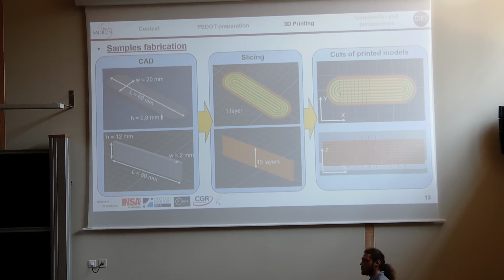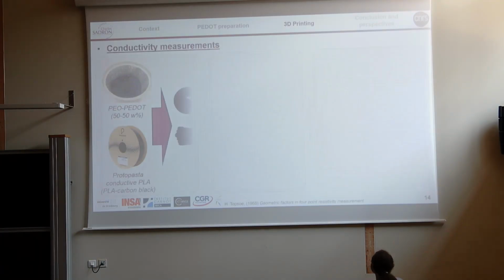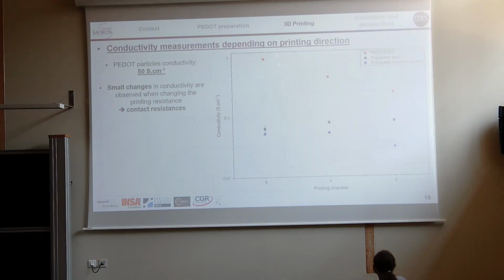And what's the gradient between the conductivity? Because we could imagine you could draw like a resistor. It was a bit documented for the Protopasta supplier values. You have kind of lower conductivity in the Z direction, not in the Y direction, because they didn't do the same. For the Y direction, they basically did what I did for the X direction. But you have this decrease in conductivity going from X to Y to Z direction, and this is what we usually observe with a composite filled with carbon nanotubes or graphene and so on.